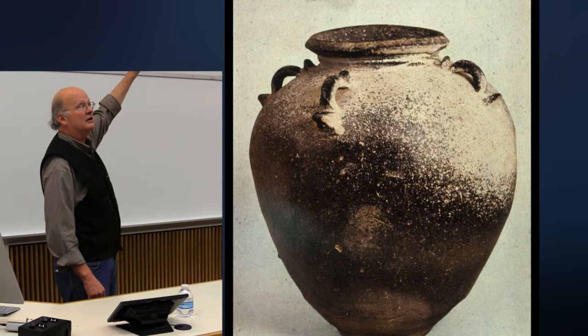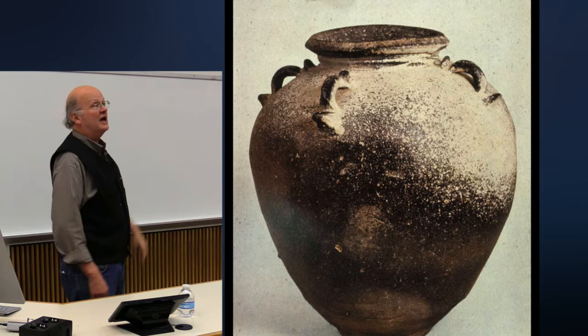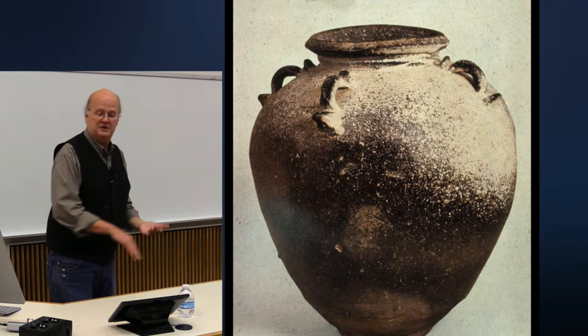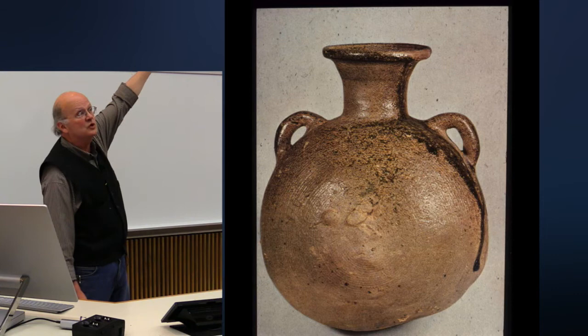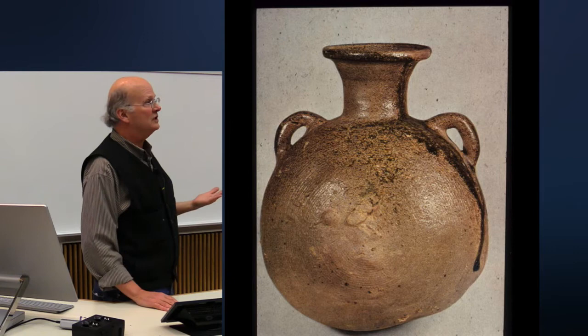Initially we had just sintering of that ash, and then as it combines with the clay and spends more time at high temperature, it develops into something that is really a glass. And you see that drip running down the side. Well, that is the beginning of glaze technology. That's where glazes come from.